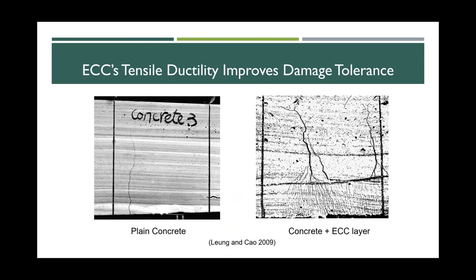And additionally, because of large tensile ductility and deformation capacity, it also improves the damage tolerance. And you see the plain concrete has formed a single crack, from the left side of the image. But once you add an ECC layer, this part is the ECC layer, you can resist the single large crack from the concrete, this part is concrete, and it diffuses into multiple small cracks. And because of the multiple small cracks, it can protect the concrete underneath and help lower the water penetration. So with such superb performance, what's the difference?